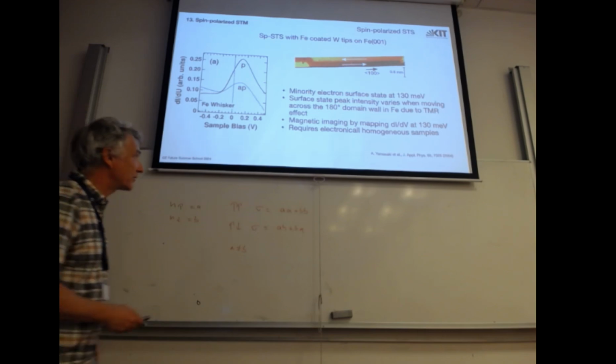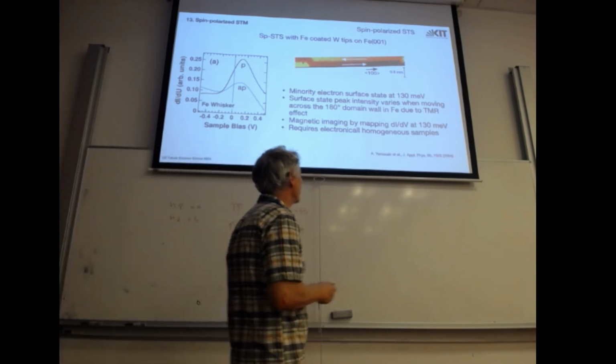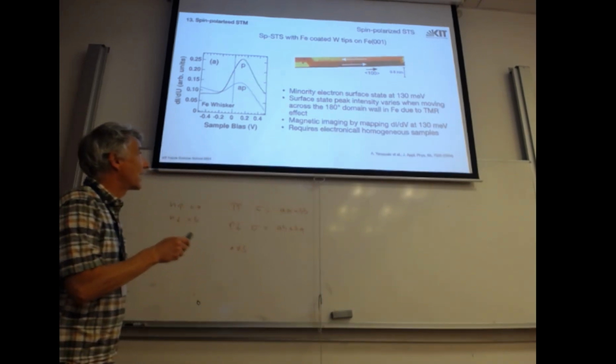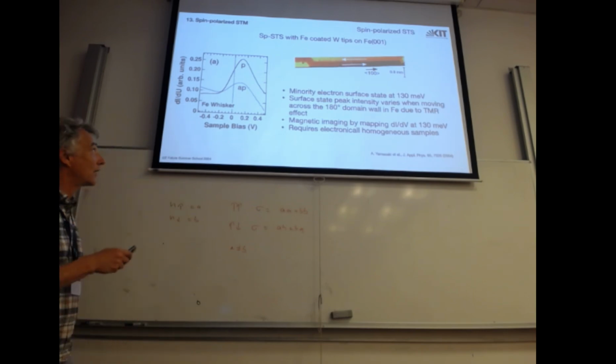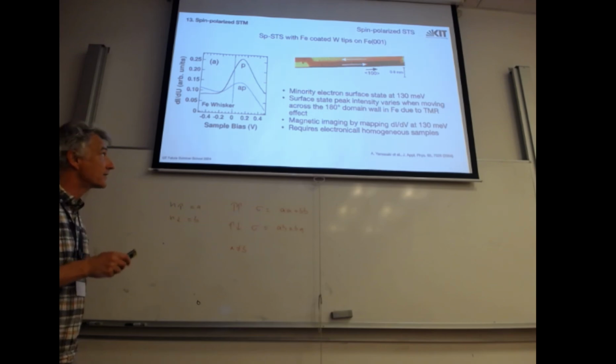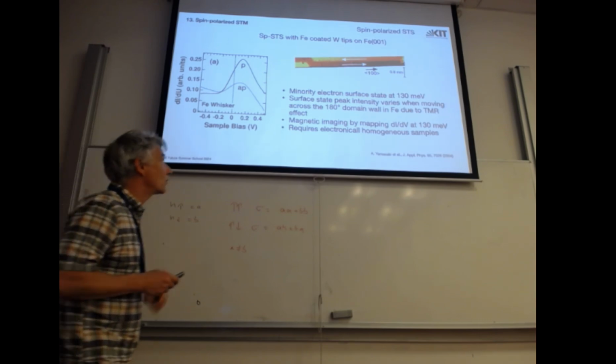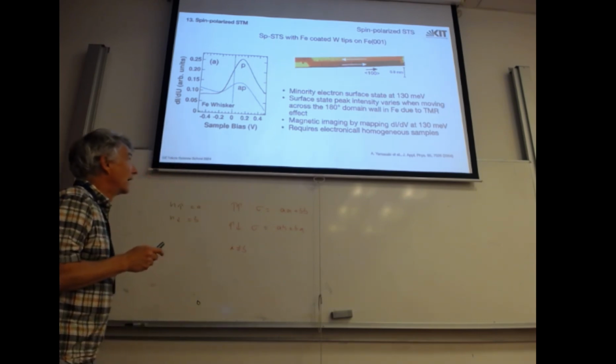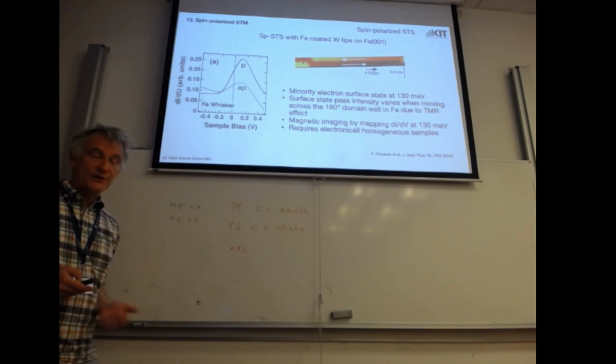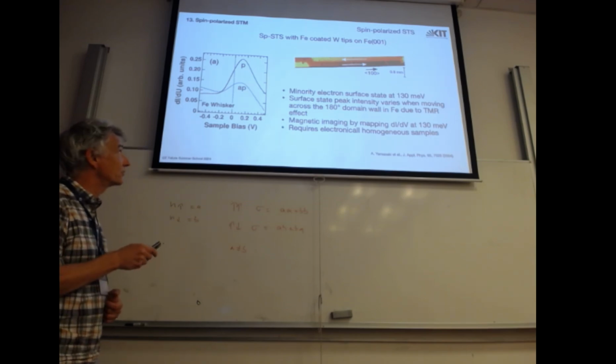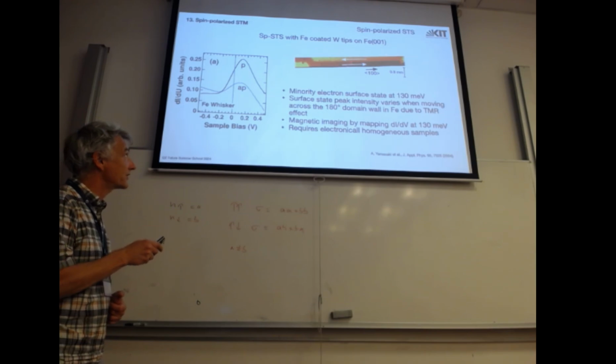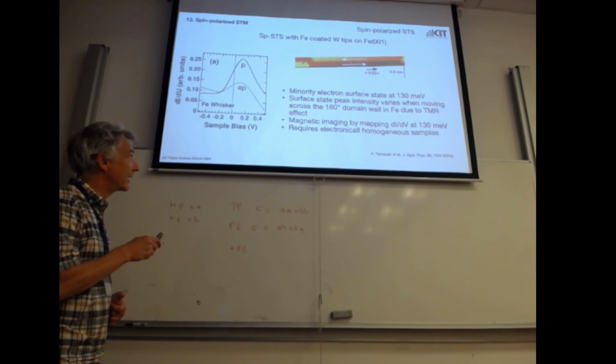So I'll give you an example from my group in 2004. We took an iron whisker, a single crystal of iron, with zero zero one directions as the axis. All of the other surfaces are also zero zero one surfaces. Since they are long and very soft magnetic, they split up into two domains, typically, or actually four domains. So the stray field is reduced by this, and there's a cap here, and then we clamp the sample.